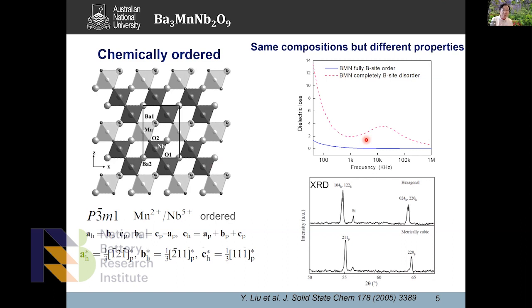In order to understand why, I very carefully ran all the samples, but instead of using 1 hour to run each sample's XRD, I ran one day, more than 10 hours, almost a whole working day. I found that some peaks are splitting and some are not. If you run quickly, you couldn't see that peak splitting.